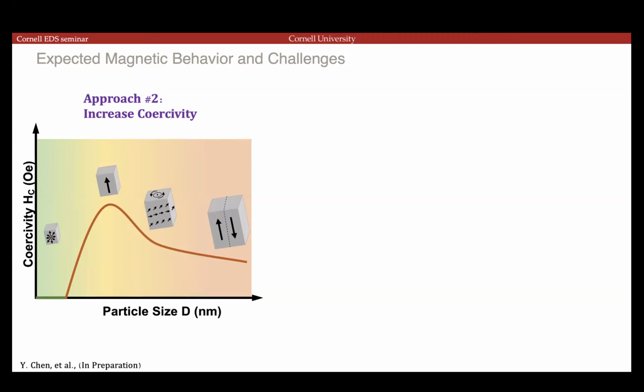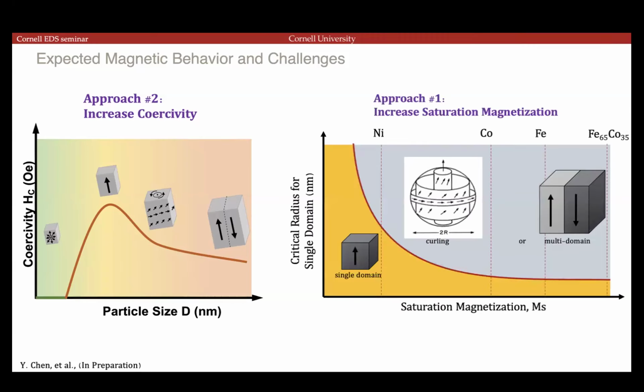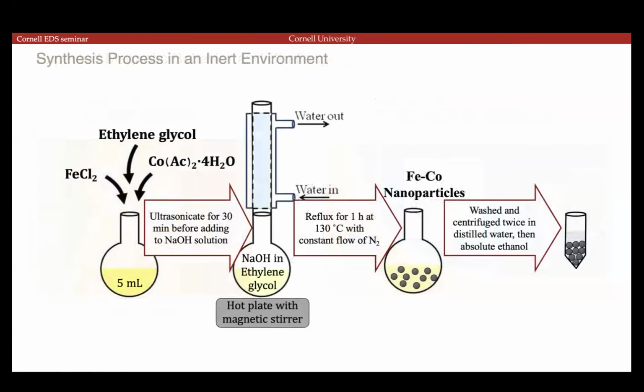So we ideally want this behavior, but the problem with increasing saturation magnetization, which was the first approach, and going towards this iron cobalt, is that as you increase the amount of magnetization that you can get in a material, the critical radius for achieving this single domain just drops significantly. So you have an even narrower range of dimensions where you can achieve the best performance. Despite all of this, we still tried to go for it, perhaps naively, but it seems to have worked.